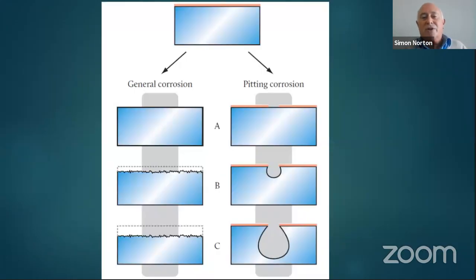So if you look at the visual that I've put up here, general corrosion, you can see on the top block, that rectangle is fully formed, nothing's happened. Then you can see how it's uniformly worn down. So you can weigh the first block marked A, and then you can weigh the next one B, and then the final one C, you can get a weight loss and you can calculate a rate of corrosion per annum. For those who work in the metric system, we would measure in millimeters or milligrams per annum, or some people measure, if they're in the USA, in mils per annum.